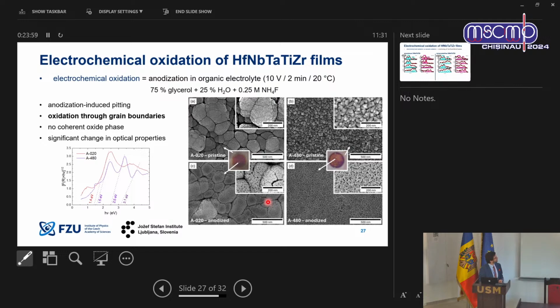Also, the optical properties of this anodized area, this round region, were much different, and when we characterized them, we observed, in case of the amorphous film, a single band gap, while in this region, you can see 2 colors, we observed 2 wider band gaps. The oxidation, as I said, it's interesting to study only the tantalum and niobium states.